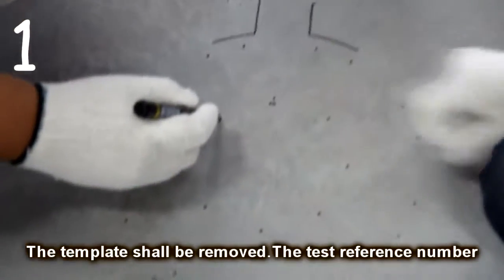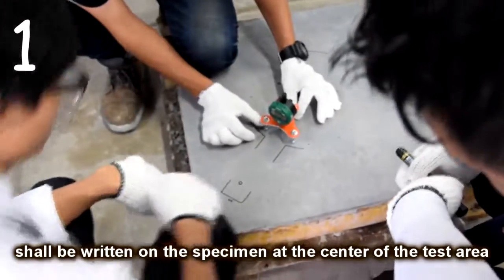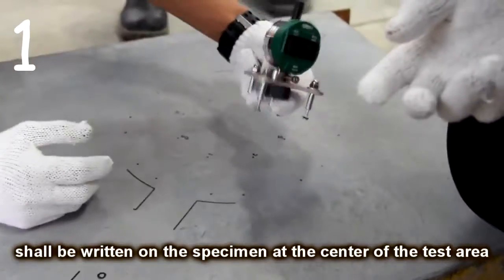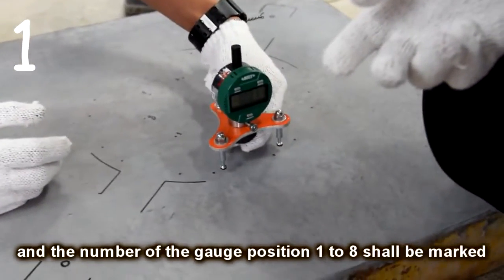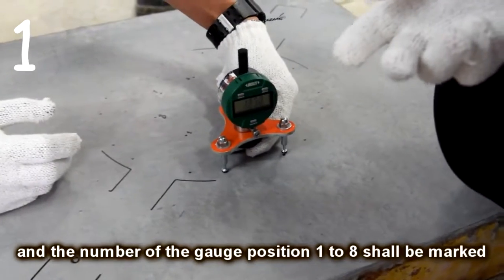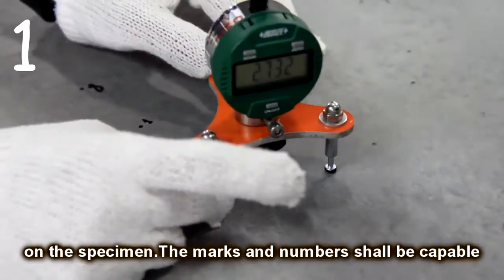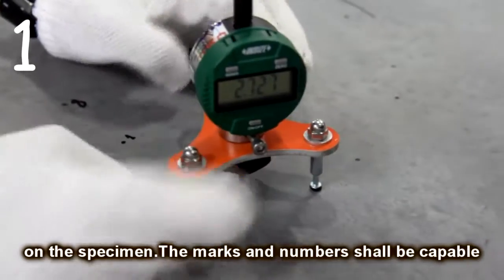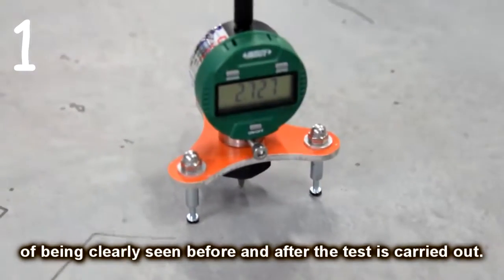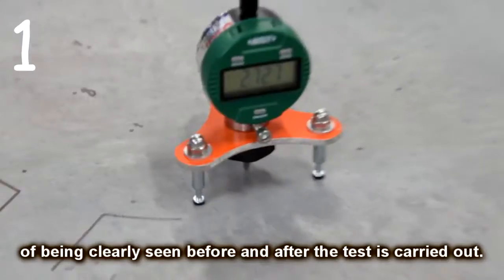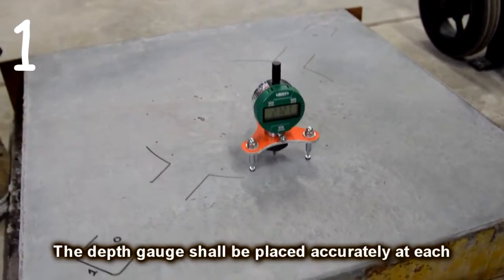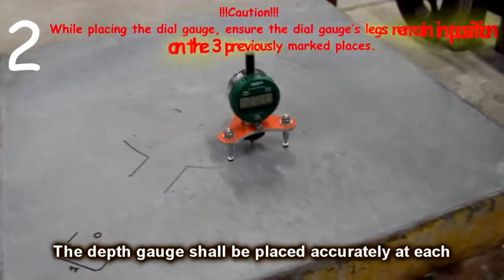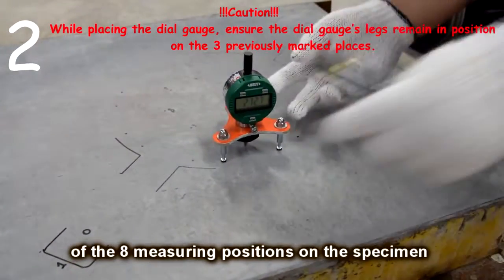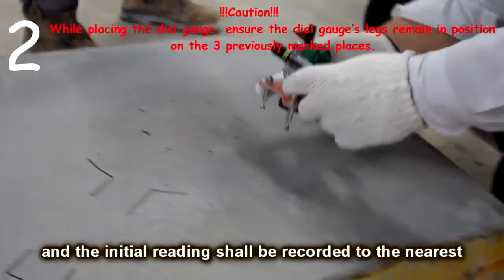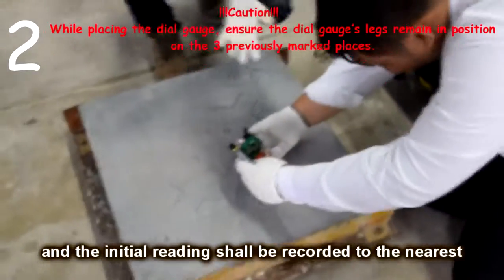The test reference number shall be written on the specimen at the center of the test area, and the number of the gauge position 1 to 8 shall be marked on the specimen. The marks and numbers shall be capable of being clearly seen before and after the test is carried out. The depth gauge shall be placed accurately at each of the 8 measuring positions on the specimen, and the initial reading shall be recorded to the nearest 10 micrometer.